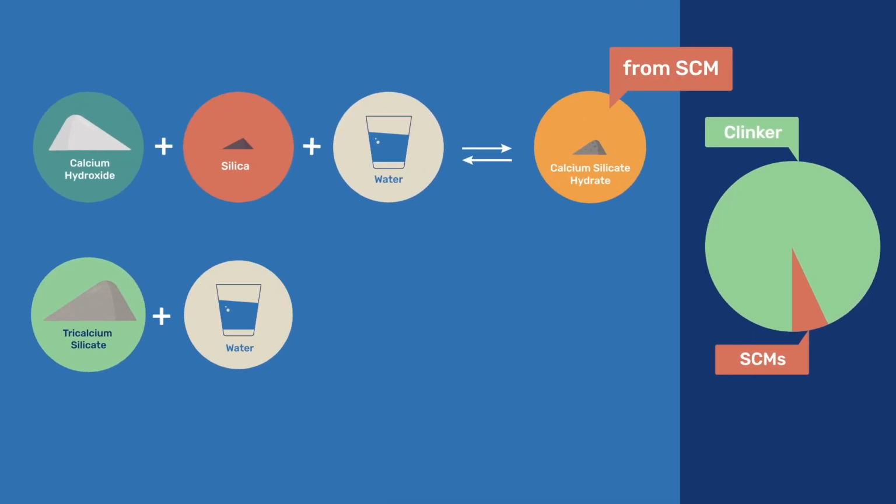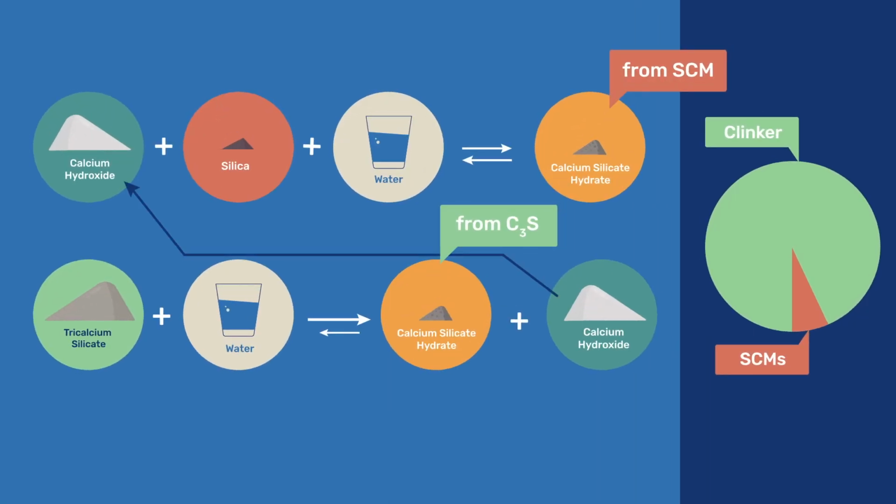First, less calcium hydroxide is produced, and second, more amorphous silica becomes available. Both changes imply that there is, in principle, a maximum level of clinker substitution by pozzolanic SCMs above which all calcium hydroxide gets consumed, so that excess SCMs cannot react fully.